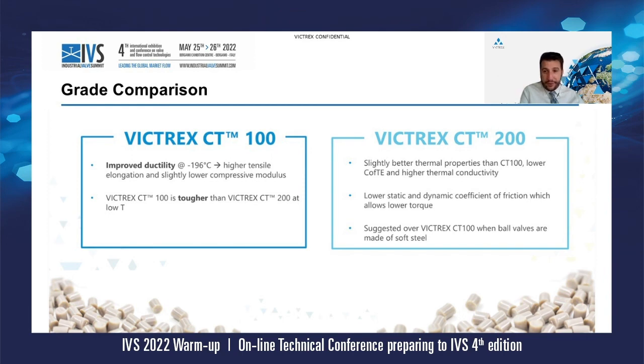For example, if you look for outstanding ductility and you want to minimize the leakage as much as possible, probably you should go for CT100. When you want to minimize the torque instead, because you know you can use a smaller actuator, you may choose CT200 in this case. If you want to reduce the wear as much as possible, you might go for CT200. If you have already hardened your ball and you know wear won't be a big issue, you might go for CT100. So it really depends.